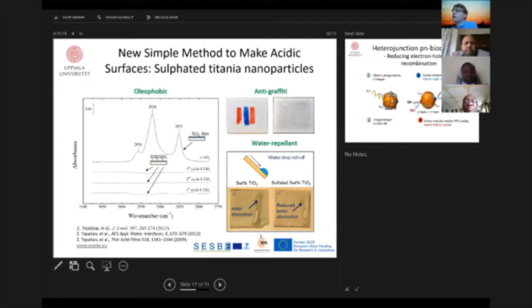Another practical application is that it's oleophobic. Here's a common titania film, and here's sulfated titania. And this is again an IR spectrum showing the stearic acid signature, which you coat. Stearic acid is a mimic of a fingerprint of grease. It's a model substance also used for ISO standardization purposes. And this is simply not present when you have it sulfated. It doesn't stick at all on the surface. And you can do anti-graffiti coatings with these kinds of coatings as well. It is very good for self-cleaning purposes. And as you may expect, water absorption is also reduced, as shown here. This is an example with a coating on a cement product.